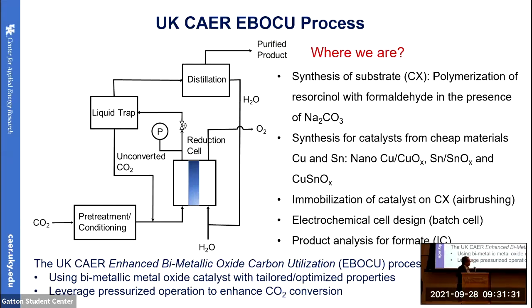We have used here commercial carbon cloth, and carbon aerogel was coated onto the carbon cloth by the polymerization of resorcinol and formaldehyde. We used very cheap metals, copper and tin, for making the catalyst. Nano copper oxide, tin oxide, and copper tin nanocomposites were synthesized using a hydrothermal process, and the products were immobilized onto the carbon cloth by airbrushing, and product analysis was done using ion chromatography.